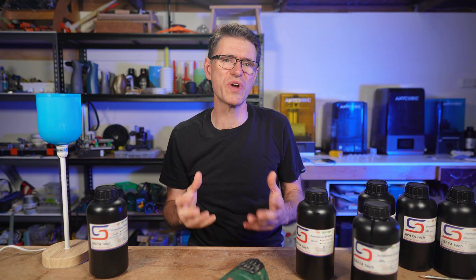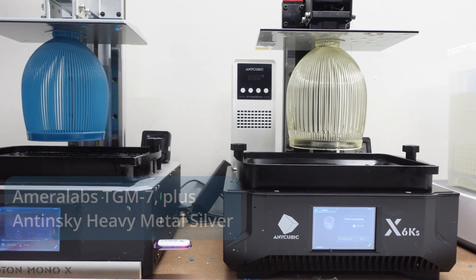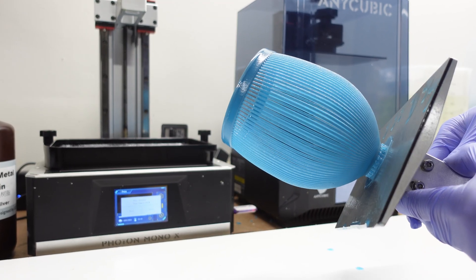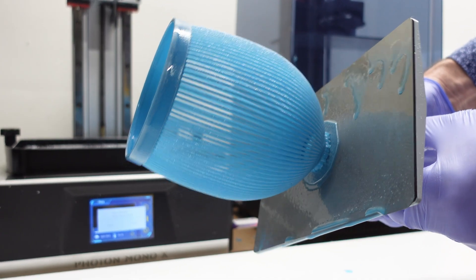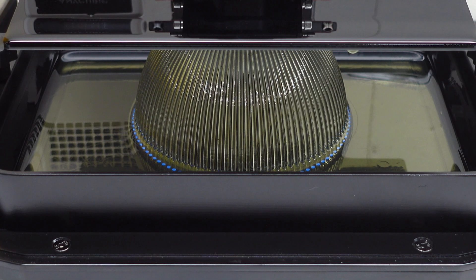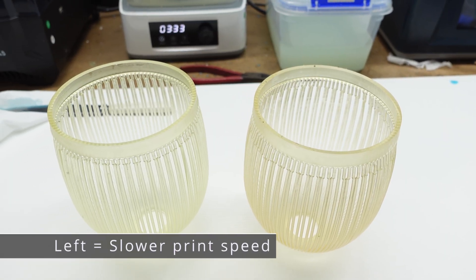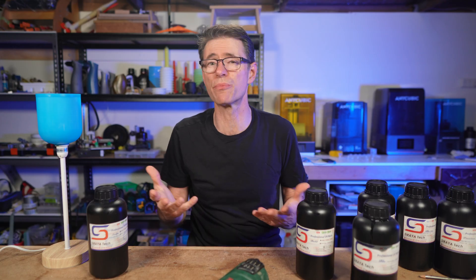What's really interesting is that the resin seems to be brittle when cured, but really flexible during a print — and I haven't seen that before. The print on the left is a mixture of Amerilab's TGM-7 and Antinsky Heavy Metal Silver. The print is flawless — the detail renders beautifully and the surface finish after curing isn't sticky and is very easy to clean. But you can't use it as a heat-resistant resin mix. The Siraya Tech Clear, however, was too flexible in printing, which resulted in the individual lines in the print sticking together near the top. I tried slowing the print down to avoid this, and that made a tiny difference but not enough to solve the problem. Siraya Tech Clear is not a bad resin — it's just not appropriate for this use case.